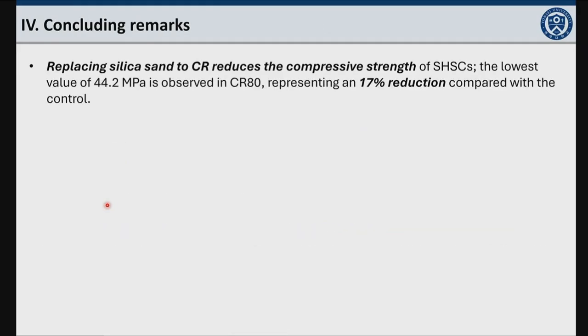And this is the concluding remarks. Replacing silica sand with crumb rubber reduces the compressive strength of the strain hardening slag composite. The lowest compressive strength of 44.2 megapascals was observed in the CR80 specimen, representing a 17% reduction as compared to the control sample.